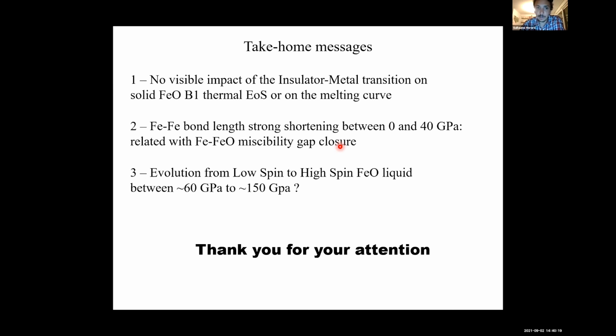Just to answer your first question regarding the FeO non-stoichiometry: it was 0.96, and this one was synthesized in a high temperature furnace by Steve Jacobson, so it was well characterized before. We also work with FeO powder, and we didn't see much difference regarding the liquid structure and the melting curve.